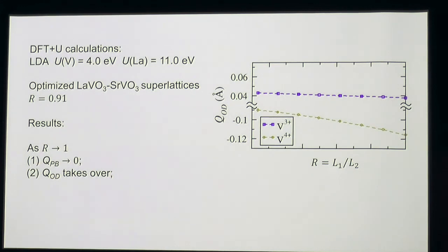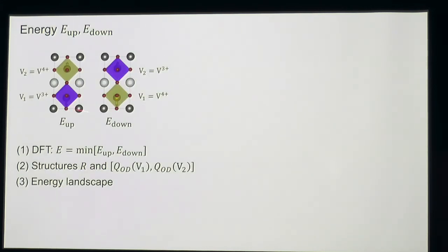To further investigate how the stability of the different polarized charge ordering states can be affected by the lattice distortion, we generate different structures with different R values and different displacements of the two vanadium atoms. And for each atomic structure, we calculate two energies of two electronic states. For the first electronic state, the bottom vanadium is vanadium 3+. As a result, its polarization is pointing up. And for the other electronic structure, the bottom vanadium is 4+ and its polarization is pointing down.